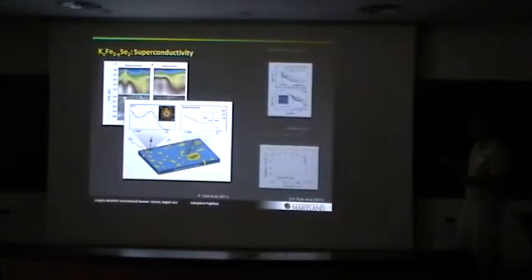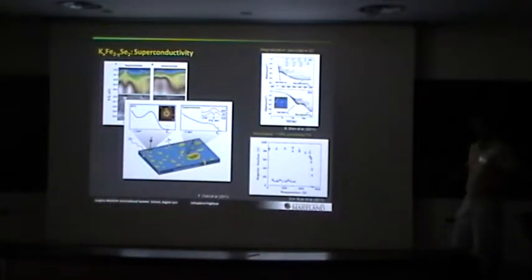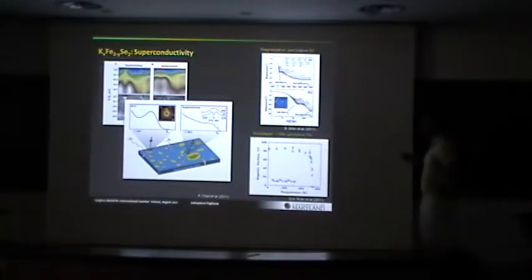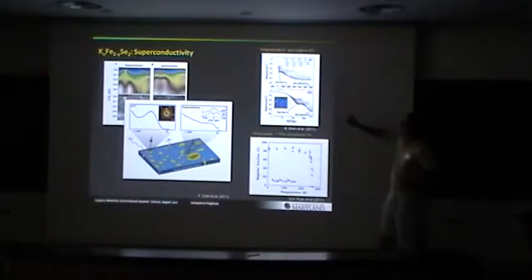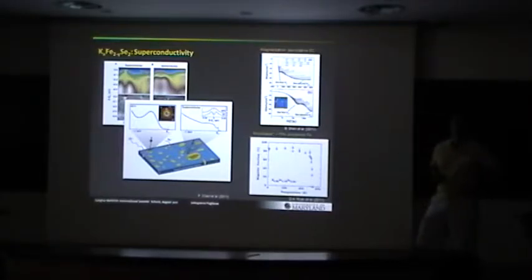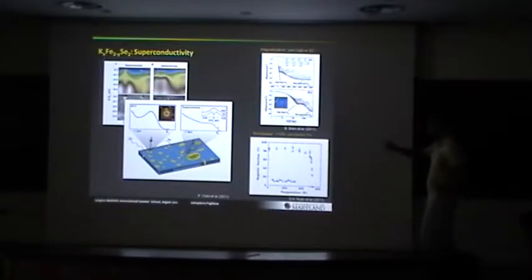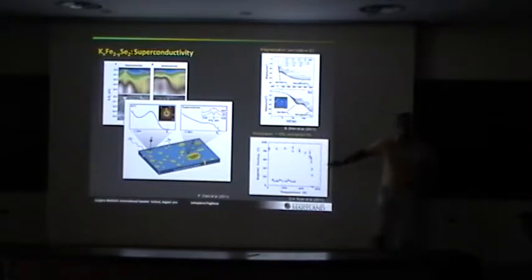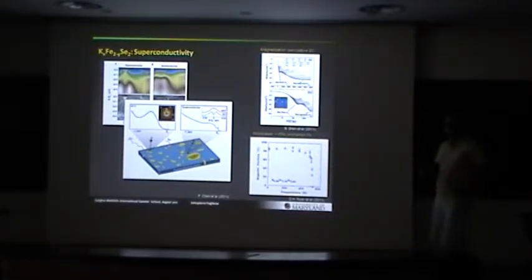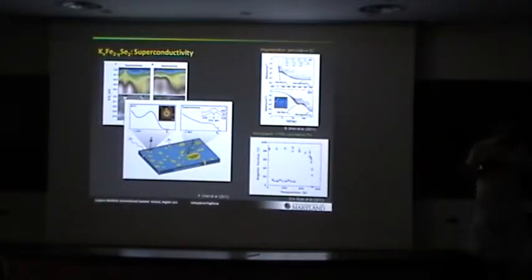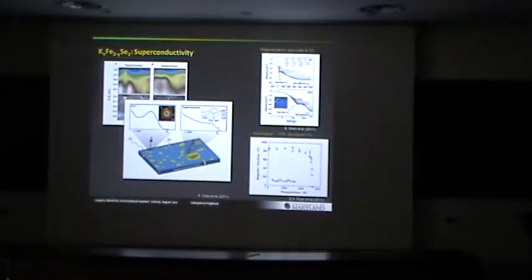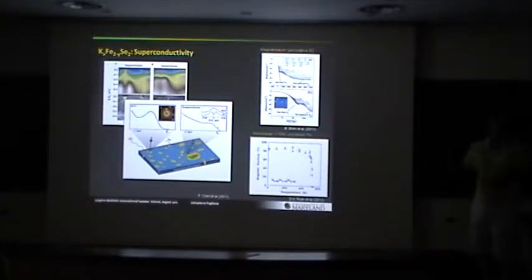Of course. So the other pieces of evidence, I value these a little bit more. Hai-Hu Wen's group has looked at magnetization in great detail, and to summarize, basically they see behavior that's consistent with a percolative superconducting state. That's one piece. And then another experiment is Mossbauer, where the conclusion is that the magnetic fraction of iron is about 85%, which means, very briefly, that you have a superconductor and there's only parts of the volume that are superconducting. You need enough to have a full percolative path to make it look like a bulk superconductor.